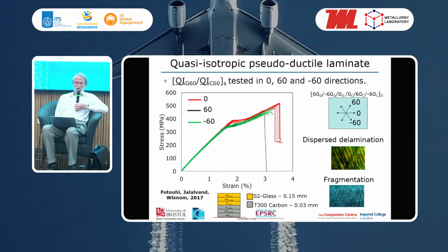So, showing you some results here. In this case, this is actually from a plus or minus 60 laminate, but again, it's S-glass and T300 standard modulus carbon. And you can see that we have a similar sort of response with a linear regime, a plateau on the stress strain curve, and then a further rising portion. And the failure modes are very similar to what we saw in the UD. We get fragmentation of the carbon plies, and we get some dispersed delamination, and that gives us this plateau on the stress strain curve.